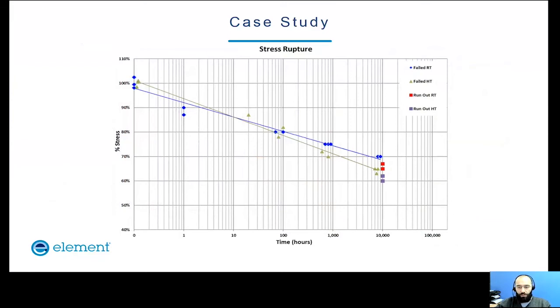What is presented here is what a stress rupture graph might look like, and it is important to point out that this graph is for illustration purposes and does not represent real life data. The pipe is tested at different stress levels, and the time to failure, which is either a mechanical failure or achieving a specific strain value, is recorded. These stress levels are defined by the experience of the test house to provide a good spread of the data over the intended period of the test. It is recommended to have a minimum of 3 data points per stress level.